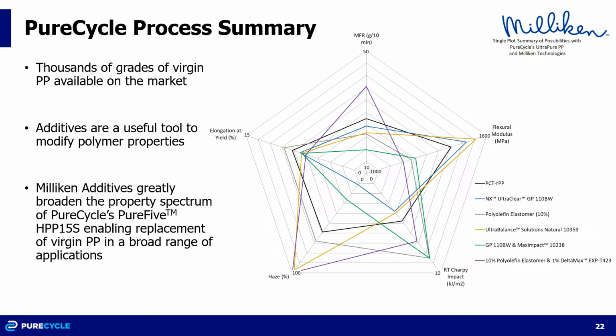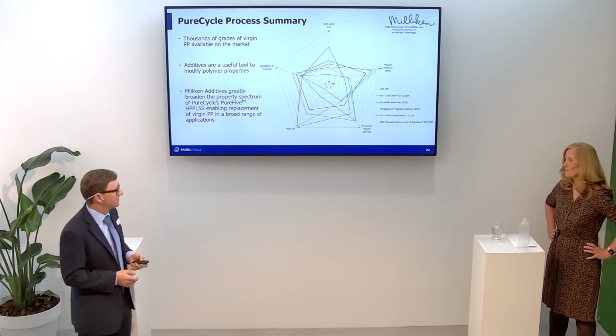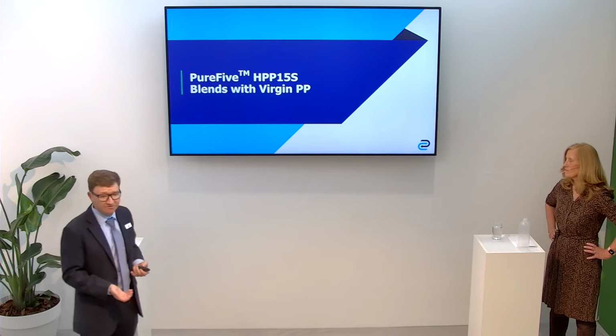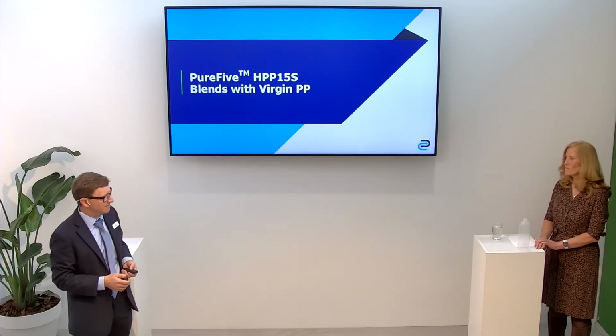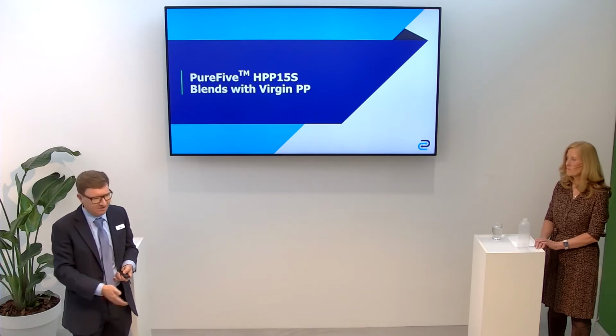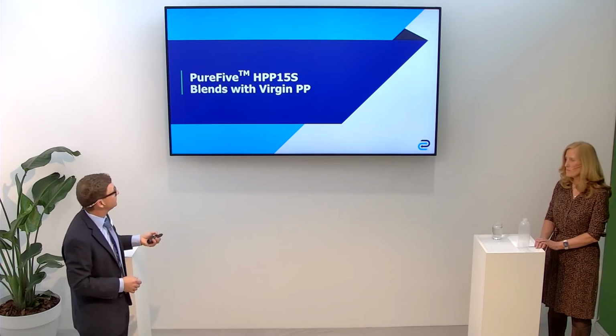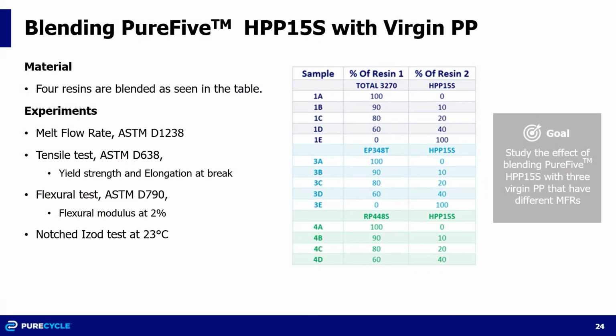There was one other topic that Rabe, their product developer, wanted me to touch on, and that's blending. As PureCycle scales, they may not have the volume to meet 100% of your needs. Additionally, a 15 melt flow is good for injection molding. We can visbreak that and make it good for TWIM, but for thermoforming it's not going to work very well, right? So you're going to have to blend a low molecular weight material, or even for EBM. For that EBM bottle, I think we blended a 2 melt flow with about a 15 melt flow PureCycle material.